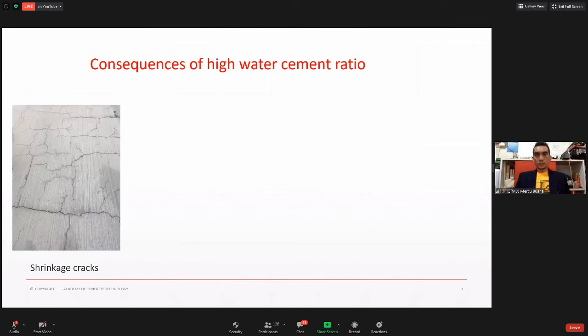You're right. All right. So these are the consequences of a high water cement ratio, right? The first thing is shrinkage crack. As you know, shrinkage cracks would appear after many months, all right? Because as you know, the water escapes from within the concrete, and that's where the stress and strains will build up within the concrete. And the concrete being very young, you might not have the strength to fight the stress and all that. So that's why for sure, any wet concrete that's delivered to the job site will have a lot of shrinkage crack. The second thing could be crazing crack.